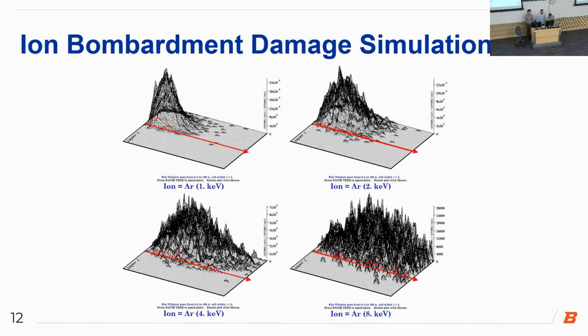Our Z-axis is a count of ions found at that specific depth. So this is more like a count of ions and how far they penetrated. Oh, it's how far they penetrate. You are not actually simulating damage, then, you're simulating depth of the argon. Yeah, the software did have counts for sputtering as well, but the fluence that we did these calculations for was very, very low, so the counts for sputtering were also very low. Often when you say a damage simulation, what I'm expecting to see is how many atoms you kicked off their site. But what you're saying is this is actually argon concentration. That's correct. Okay.